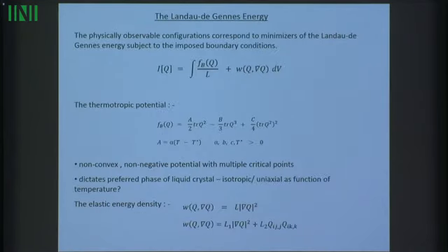So it's a variational theory, so we have the concept of a free energy. There can be many complex forms of the Landau-de Gennes free energy, but I largely work with the simplest one, and that's actually hard enough from a mathematical point of view. But if you look at the energy density, you will see that I effectively have two contributions. I have a bulk potential, which is Fb. If you look at my formula, you will see that my Fb, which is the bulk potential, is a quartic, degree 4 polynomial in the eigenvalues of the Q tensor.